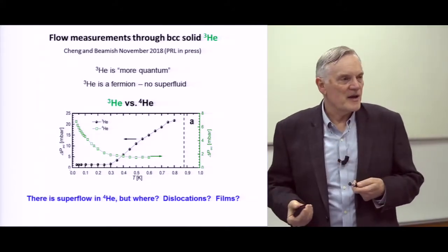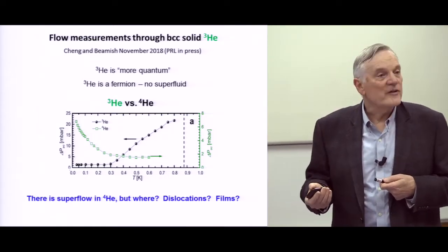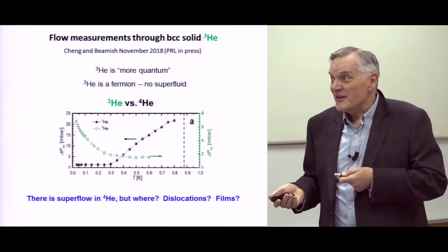So in more detail, in these papers we published, we looked at the amount of helium-3 that was required in our experiments. Our conclusion was it's hard to understand unless it was a 2D channel, a film somewhere. It took more helium-3. There's a neat place that the helium-3 may block all those other experiments with the superfluid leads, which is the favorite place for helium-3 ever, at the interface between liquid and solid helium-4. It's tightly bound there. So in principle, that's where it goes. And by some kind of coincidence, in the Vycor experiments with the superfluid leads, they always block pretty much where there's one monolayer of helium-3 on that interface between liquid and solid. Helium-3 doesn't dissolve into helium-4, so that's either a coincidence or a clue, but in our experiments without the liquid, it took a lot more helium-3 to block the channels. So we're suspicious that it's not in one-dimensional channels.